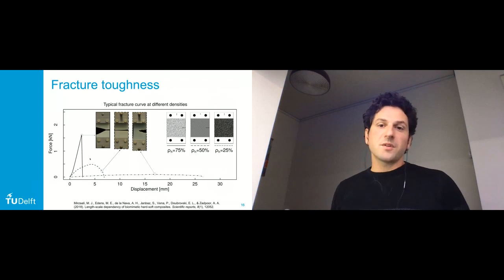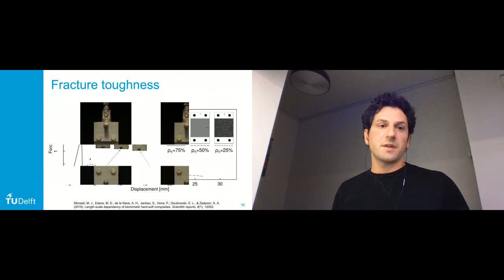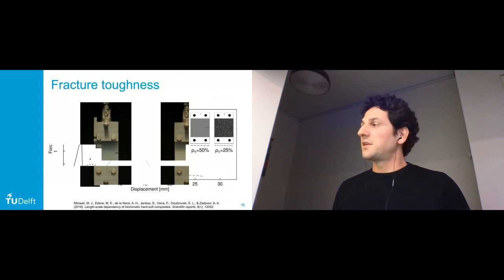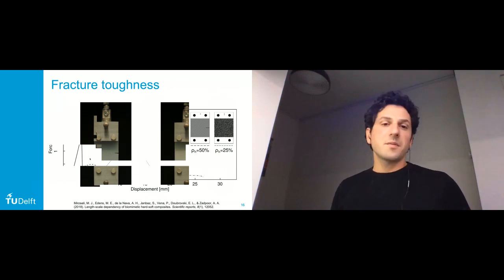And also, using this voxel-based multi-material additive manufacturing, we've been looking at understanding how the different ratios, the different printing patterns, and the scale of these patterns can influence the fracture toughness of the resulting part. Some combinations of these variables have been found to really strongly influence the fracture toughness, as can be seen in these two 3D printed samples that are tested. So the material distribution is similar of flexible and rigid. However, the printing pattern is significantly different, having a very large effect on the fracture behavior.